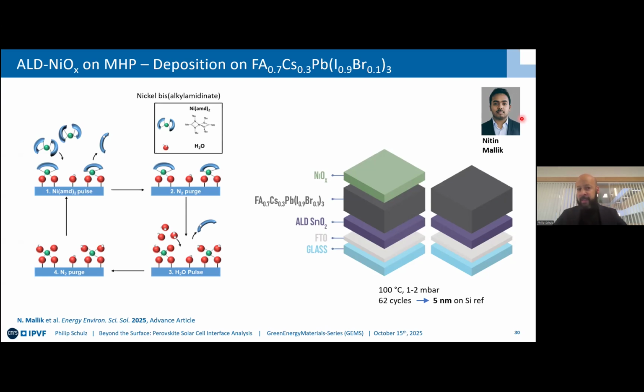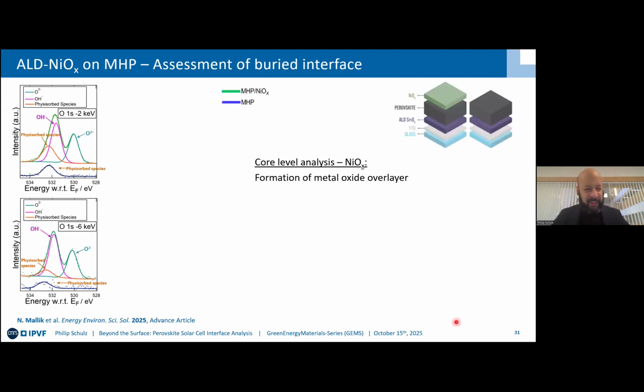Here, it's really the same thinking, same approach, but we exchanged the precursors. The nickel source, in our case here, is nickel bis alkylamidinate, whereas the oxidizer is H2O, so water, effectively. Again, we're aiming to get to a nominal film thickness of 5 nanometers. This time around, I'd like to spend a minute or two going a bit deeper into the property of the oxide itself. I didn't show it before for the tin oxide, so you can take my word for it. Except for the slight changes in peak positions, the tin oxide showed up to be very stoichiometric, regardless of whether you measure it at 2 keV or 6 keV.